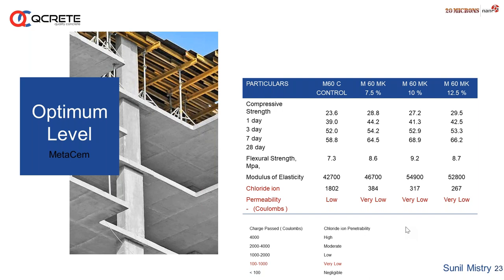Whereas by replacing cement by 7.5%, it is giving 28.8. It increased by 5 MPa. And by replacing a little more cement, by 10%, it gives 27.2, and by 12.5%, it increased to, this is the first day result, and on 28 days, if you see,